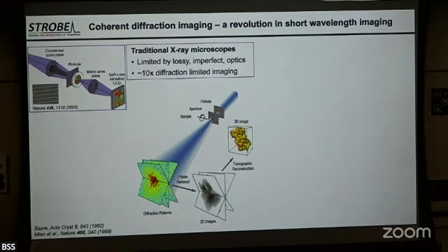If instead of sticking the image forming lens in, one feeds the scatter pattern into what's called a phase retrieval algorithm that are used ubiquitously in science, you can actually recover the image and there's no optics between the sample and the detector. So that means there's no aberrations. So suddenly you went from 10 times the diffraction limit to just numerical aperture. So instead of 10 lambda spatial resolution, you can get to lambda over 2. So that's a big deal in X-rays because it really improves the spatial resolution of the X-ray microscopes.